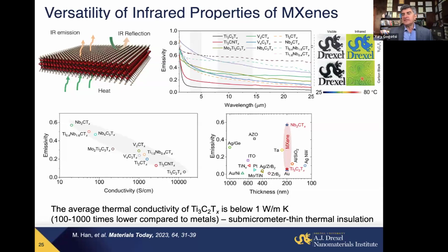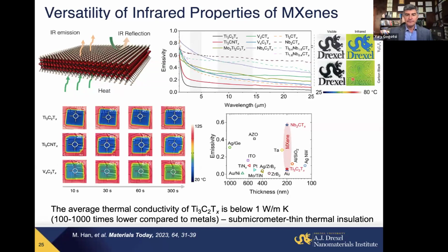Carbon will be heated just like the environment. We put it on a 125-degree heated plate. And you can see even after 5 minutes, basically stabilizing the temperature field, it's only 40 degrees. So more than an 80-degree temperature drop from a 200 nanometer film.